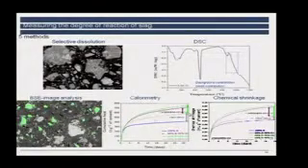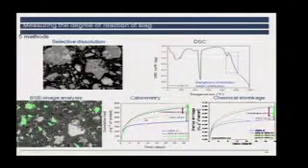And we can see here that we have, first of all, the filler effect I already explained, and then above and beyond the filler effect, an extra heat here, which comes directly from the reaction of the slag. And by subtracting the grey filler reaction from these purple and green reactions, you can get an indication of the amount of reaction of slag. So that's very nice. It's a continuous method.